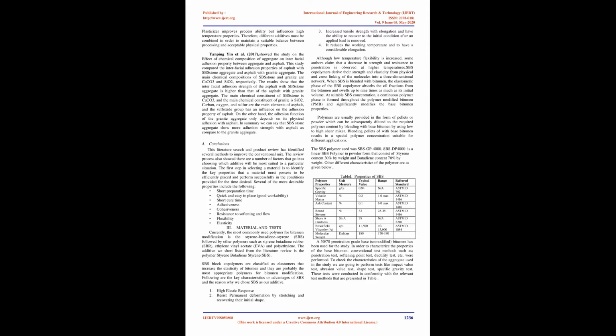The addition of RHA could significantly improve the rutting resistance of HMAs at different stresses and temperatures, which could be attributed to the improvement of rutting parameter and elastic behavior of modified binders. Also, the rutting performance of HMAs with 15% RHA and 20% RHA are almost similar according to fatigue test results. Mixtures containing RHA exhibited better fatigue life compared to control mixtures. This enhancement might be due to reduction of air void in the mixture and/or improvement of adhesion between binder and aggregates. The mixture with 15% RHA had the highest fatigue life.